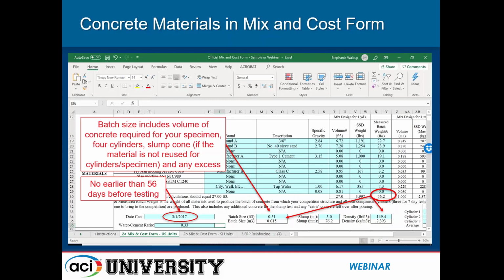The measured batch weight should be equal to the density of your concrete multiplied by your batch size. So if we take 149.4 pounds per cubic foot and we multiply it by the batch size of 0.51 cubic feet, we see that we get the measured batch weight of 76.2 pounds. So again, these are checks that you should be making when you're filling out your official mix and cost form.